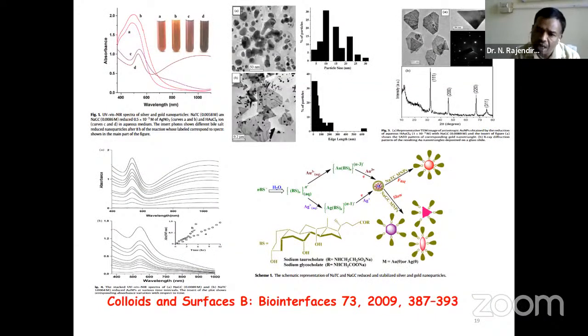Even though plant extract is of low toxic or biocompatible nature for the preparation of metal nanoparticles, the drawback is that once you prepare the metal nanoparticles using the plant extract, the stability is a question mark. Mostly these metal nanoparticles are stable up to 1 week or 2 weeks only. If you go for applications or long-term purposes, they should be stable, but stability is the problem. The other thing is that in the plant extract there are a lot of constituents, so we cannot exactly say which constituent is responsible for the reduction of metal ions. That is also a problem. The third thing is reproducibility, because when you try to prepare the nanoparticles using plant extract at a different time, you cannot get the exact concentration. So reproducibility is also a problem in plant extract.